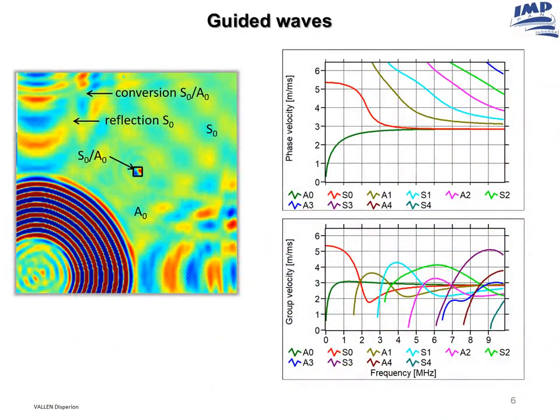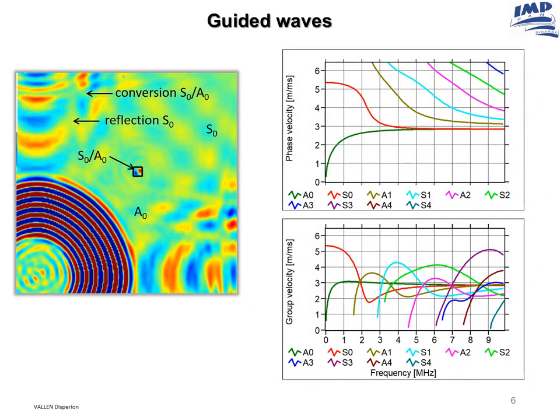The first method I would like to introduce is Guided Wave Propagation. Guided Waves are elastic waves that propagate in thin-walled structures. They propagate in a multi-mode nature, with so-called anti-symmetric modes and symmetric modes that propagate with various velocities in the material. Depending on the frequency, more than one mode can propagate in a structure. At a defect location or other discontinuity, such waves are scattered, reflected, and converted to other modes. The figure on the left shows how the propagating symmetrical mode S0 is converted to the anti-symmetrical A0 mode.